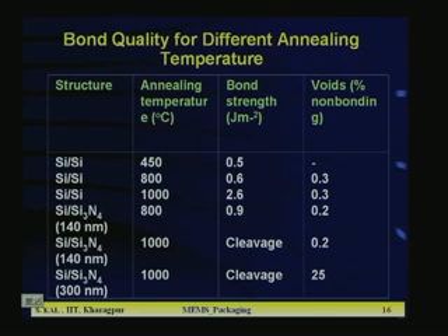You can see here, when you go for silicon and silicon bonding at 450 degree C, the bond strength is 0.5 joule per meter square. And void formation, void means what? Non-bonding. Particular points where there is no bonding, they leave a void, and voids are not desirable. If a lot of voids are there, the bonding will be highly weak, isn't it?